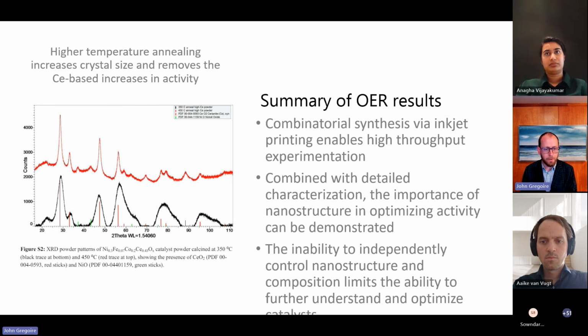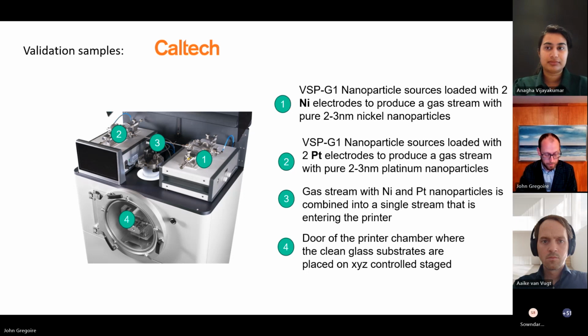But as I alluded to with the ink formulations, we can discover interesting nanostructures, but we have very limited control over that nanostructure. We have to use the thermal processing required to burn out all the components of the ink that we're not interested in and convert these to metal oxides. In that one composition we saw, with 50% cerium and a mixture of transition metals, it provides a very optimal nanostructure as far as we know, but we have limited ability to independently control composition, processing, and nanostructure. And so for that, we're really looking to a future of synthesis techniques where we can gain control of those various axes.